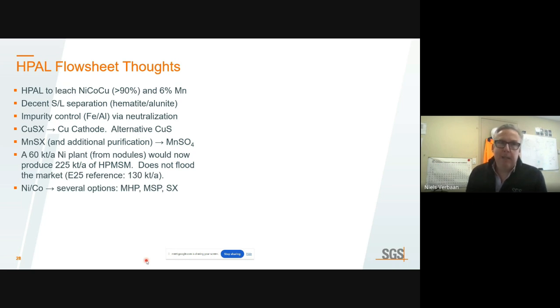The little bit of manganese that is there, the 5 or 6% that's extracted, can be recovered. It could be processed into manganese sulfate. And it's actually of interest to note that if we go back to the 60,000 ton per year nickel style plant example, now this would produce, if all of the manganese that was leached goes to high purity manganese sulfate, now we're looking at around 225,000 tons per year of the manganese sulfate. Now, that is more in line with current market examples of manganese sulfate producers. And I refer back to the E25 example that is making under 130,000 tons.